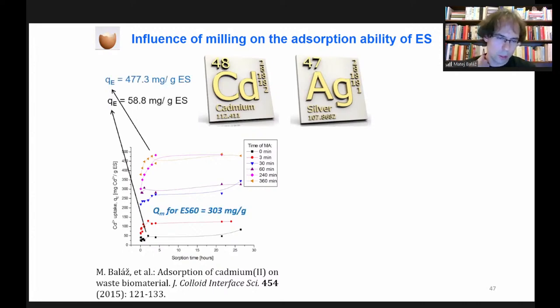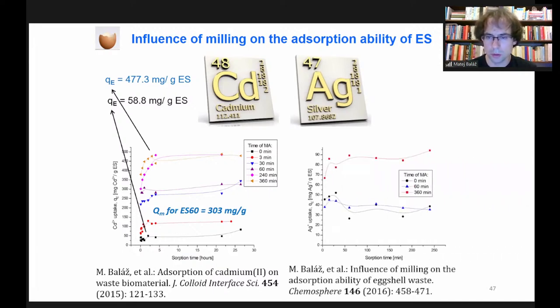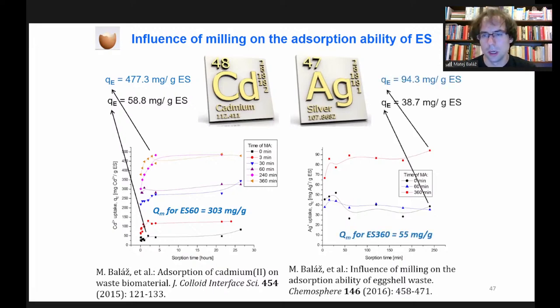At the end, we ended up with a maximum sorption capacity of more than 300 milligrams per gram, which is a really good value in comparison with other biosorbents that are usually used for cadmium adsorption. With regards to silver, the process was not so efficient. However, again, after 6 hours of milling, we observed some increase of adsorption ability. We are thinking it's mainly connected with the presence of the aragonite phase. Here we can see that the maximum sorption capacity is only 55, in comparison with more than 300 in the case of cadmium.